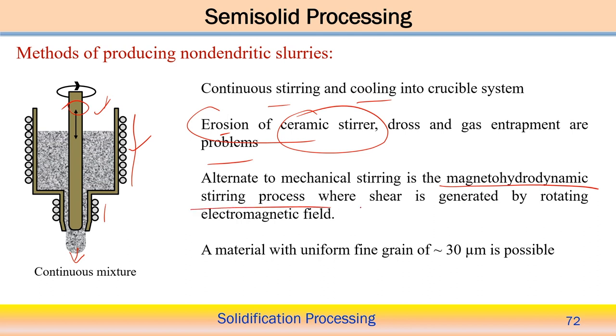So in the magnetohydrodynamic stirring process, the shear is generated by rotating the electromagnetic field. Simply by controlling or rotating the electromagnetic field, the shearing action is imposed on the liquid metal, and this process can avoid mechanical stirring of the liquid metal. If we follow this process, a material with a uniform fine grain of 30 micrometers is possible to achieve by this technique.